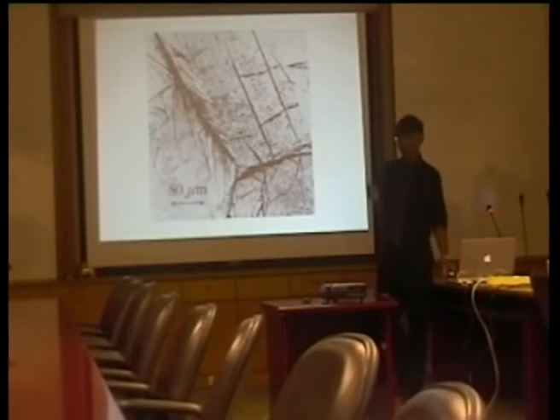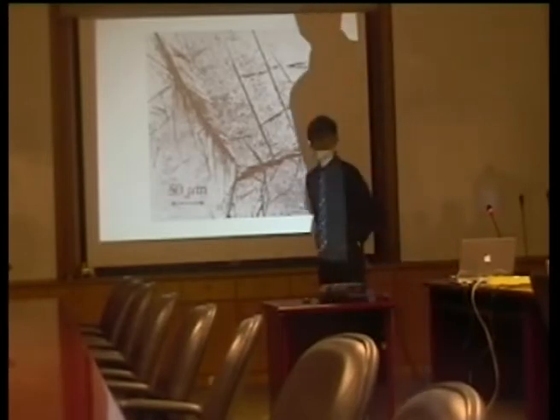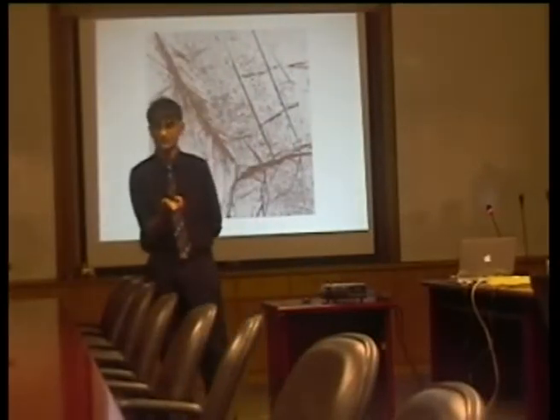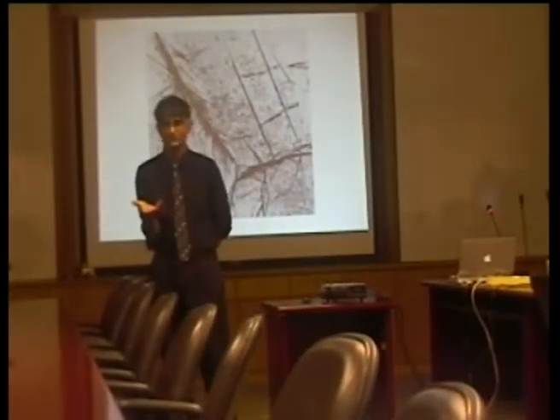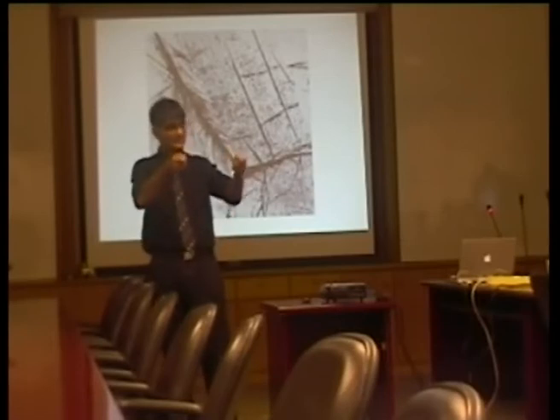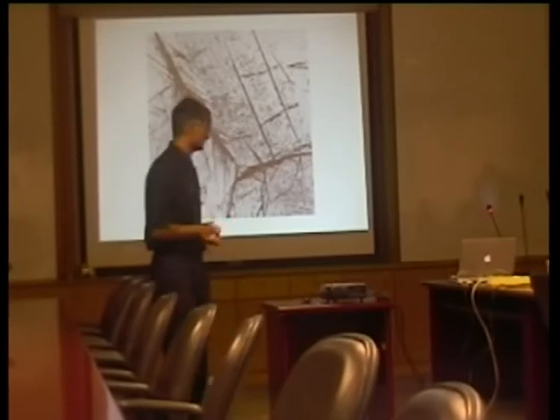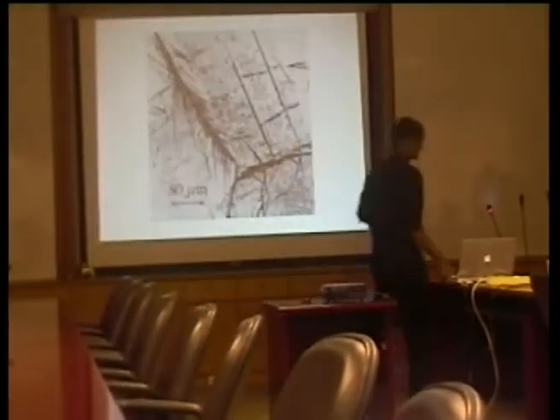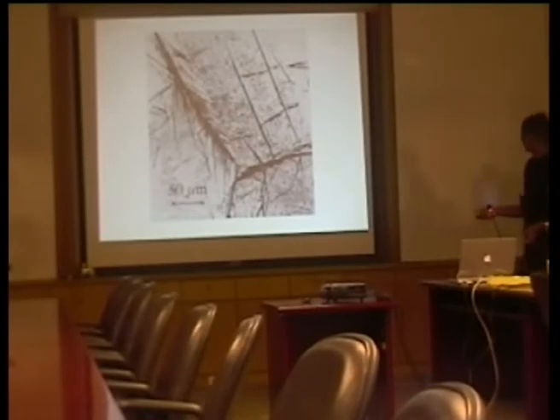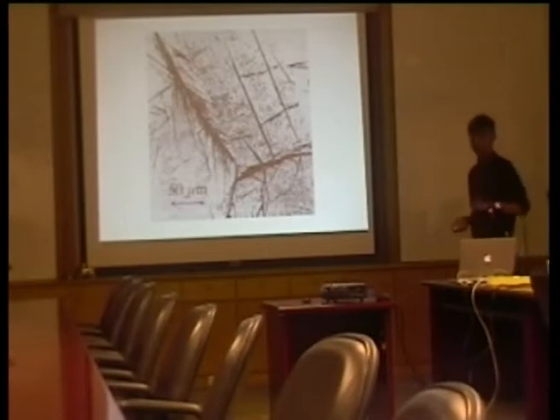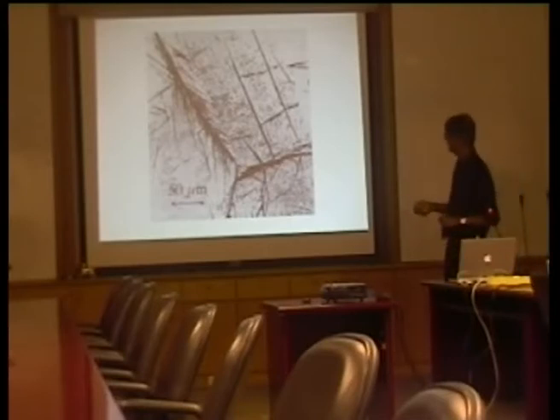This is the other steel to which we have applied the theory. Okay, so this is the 0.4 carbon, 3 manganese, 2 silicon alloy. Ordinary ferritic steel, where we austenitize it and we transform it to bainite. So this is what it looks like in the optical microstructure. These are plates of bainite in a matrix of martensite because we have partially transformed this to bainite. Now, this is an optical micrograph. You can see the scale here.